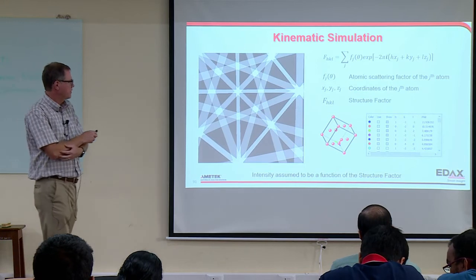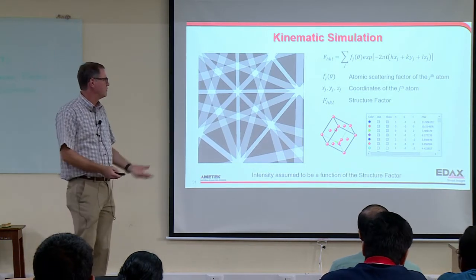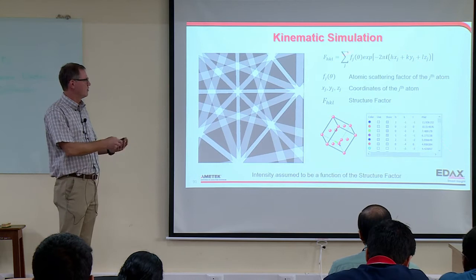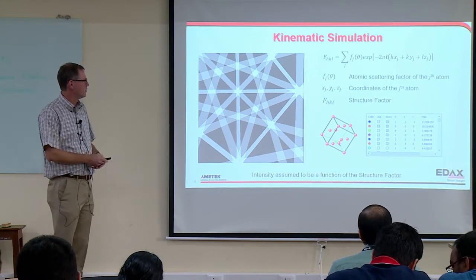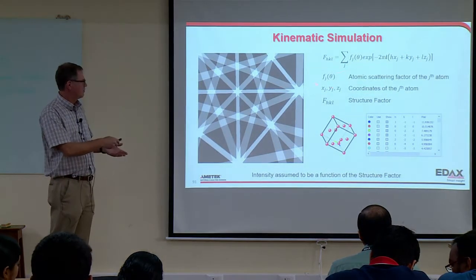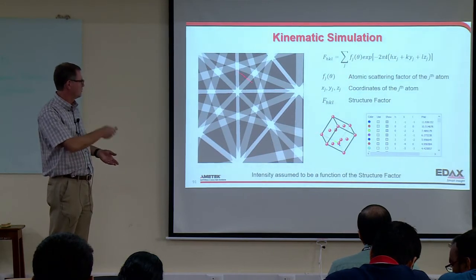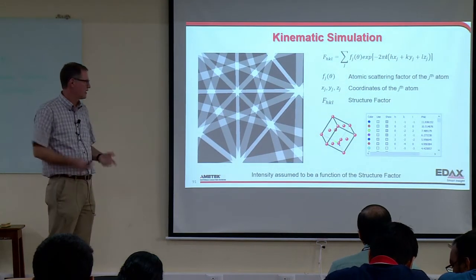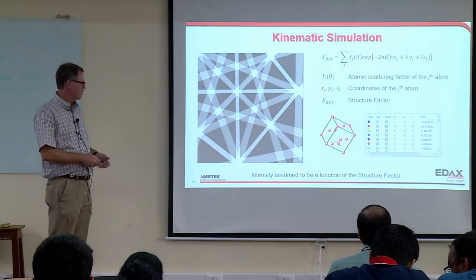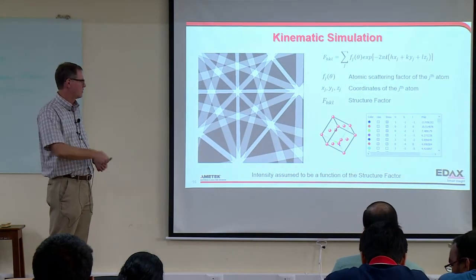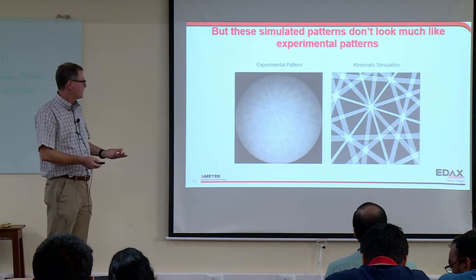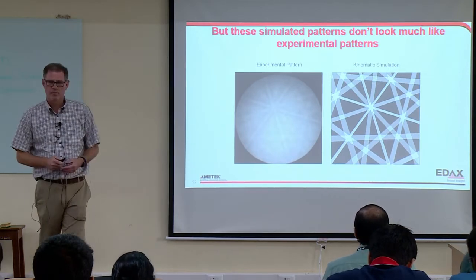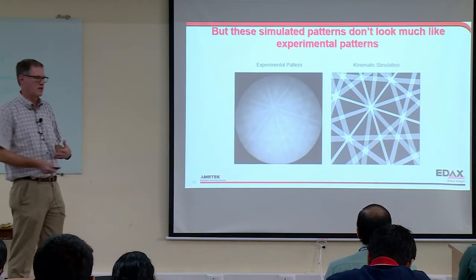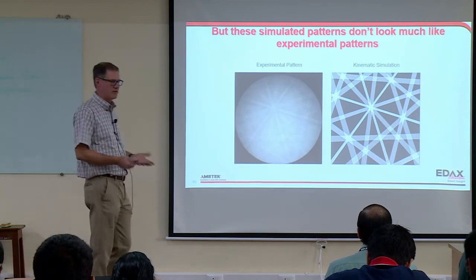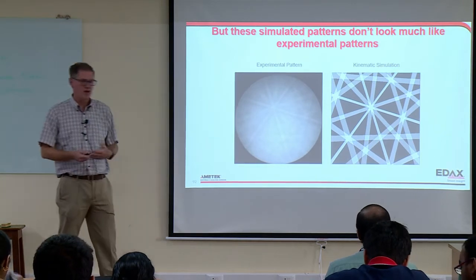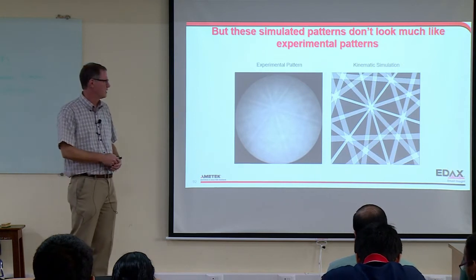So kinematic simulation we've been doing since the beginning of EBSD, and I mentioned this equation earlier to calculate structure factors. So we find the planes with highest structure factors, and we can draw what a pattern would look like approximately, because we know the intensity's a function of the structure factor. And that's great, but it doesn't really look like experimental patterns. The general location of the bands is there, the width of the bands. Those approximate things are there, and that's helpful. It's gotten us this far, and we can do a lot with what we have today.